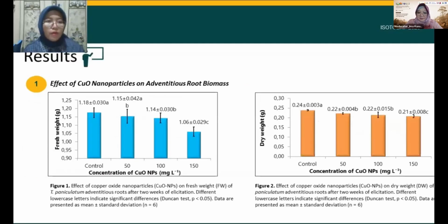Next, results. 1. Effect of copper oxide nanoparticles on adventitious root biomass. Copper oxide nanoparticle elicitation significantly affected biomass production in adventitious root culture of Talinum paniculatum. Fresh weight decreased progressively with increasing nanoparticle concentration, and dry weight exhibited a similar response pattern. The control treatment produced the highest dry biomass, whereas treatments with copper oxide at 50 mg and 100 mg significantly reduced dry matter accumulation.